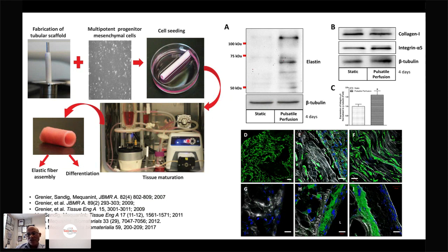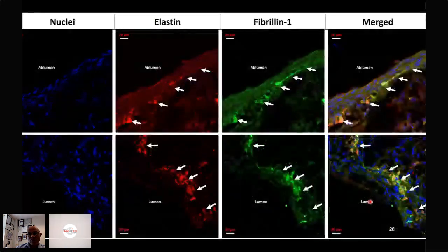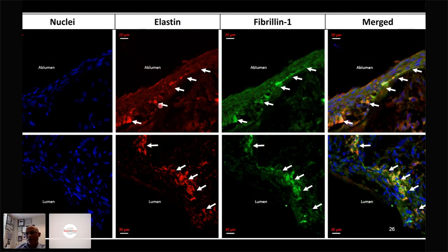One of the challenges in vascular tissue engineering was the absence of elastin production, and we were able to use different techniques to produce elastin, and just to compare it with rat elastic tissue here, the top one is a control, and the bottom one is our product, and you can see that in the engineered tissue, elastin was expressed quite abundantly. We also looked at elastin cross-linking. When elastin is cross-linked, it requires the scaffold protein called fibrillin 1. Every time we do these tissue fabrications where we see elastin, there was also fibrillin, and therefore this indicates that we were producing a vascular tissue which contains cross-linked elastin.